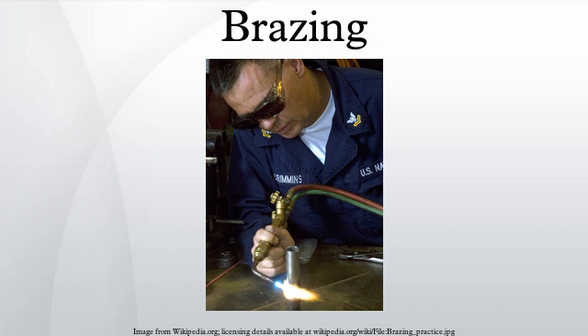Dip brazing. Dip brazing is especially suited for brazing aluminum because air is excluded, thus preventing the formation of oxides. The parts to be joined are fixtured and the brazing compound applied to the mating surfaces, typically in slurry form. Then the assemblies are dipped into a bath of molten salt which functions both as heat transfer medium and flux.